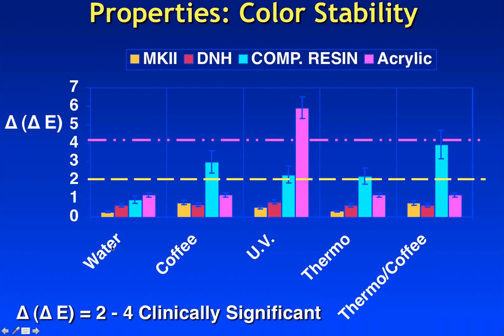And these are a variety of tests that people use: water, coffee, ultraviolet light, thermal cycling, and thermal cycling followed by coffee. Now, why do we do this? Well, for materials with 2 phases, like a composite resin or the Enamic material, there may be an issue of the polymer separating from the particles, and so eventually you'll get percolation in between the particles and the polymer, which would be highlighted by the dark coffee going in between the polymer and the particles. This is really a very good stress test on material to see how well there is a bond between the particles and the polymer, because the coffee will go in between those two if they start to debond.